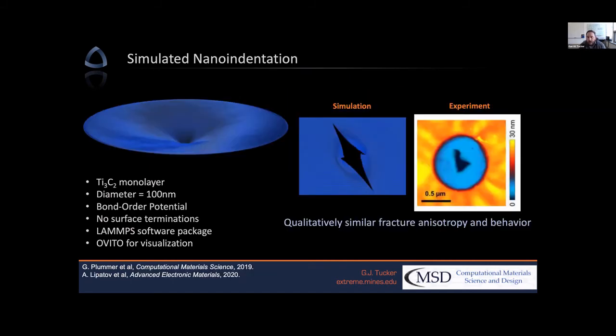And so if you were to take a snapshot more or less of the end part, this specific one is for a Ti3C2 monolayer. Once again, the diameter is 100 nanometers. And we compare the simulation to experiment. And we understand the length scales are different here, but we see qualitatively similar fracture and anisotropy and behavior here. So this gives us a little bit of confidence and motivation to keep going. And like I said, we want to add in these surface terminations, which we're doing. But now we have the numerical framework, we can scale this up into much larger systems to really get after and connect better with those experimental studies.